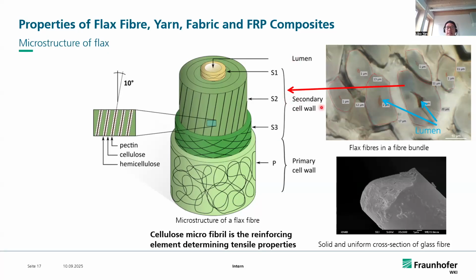The secondary cell wall can be further divided into S1, S2, and S3 layers. The S2 layer has the largest thickness and contains most of the microfibrils. The cellulose microfibrils are the components that determine the tensile strength and the tensile modulus of the flax fiber.